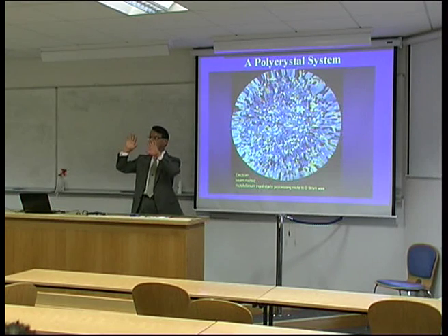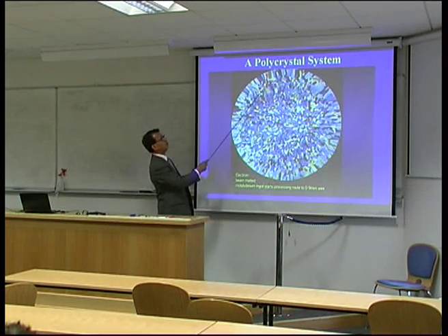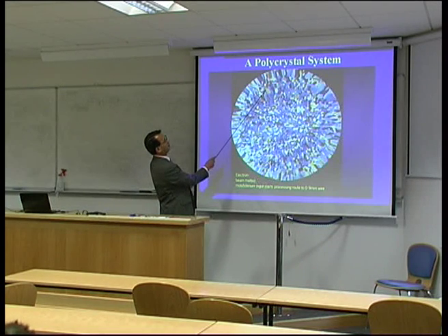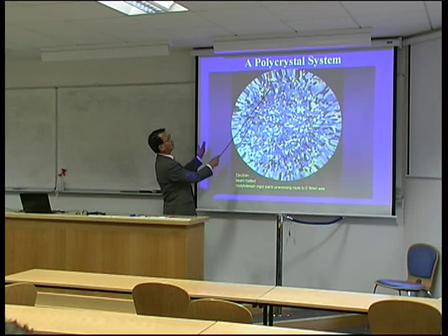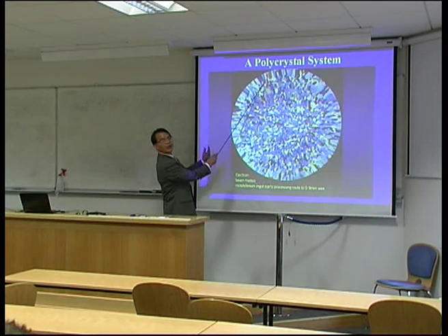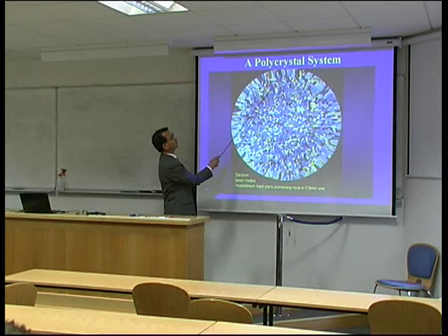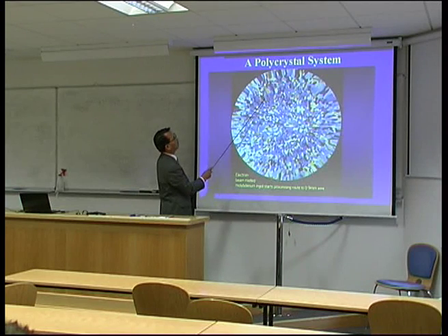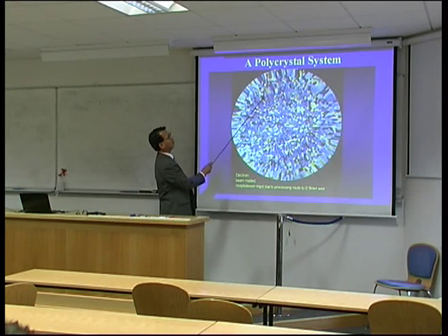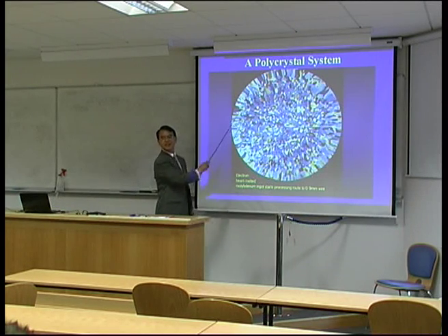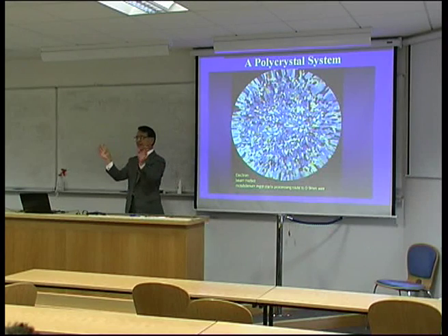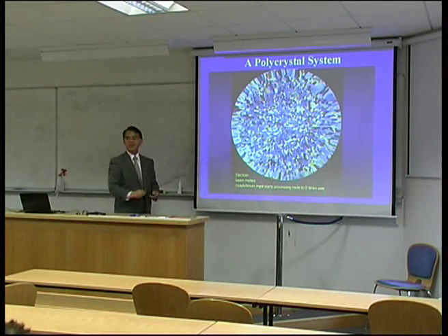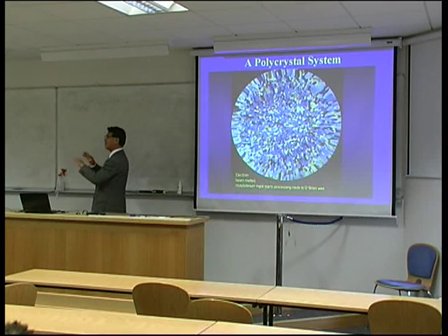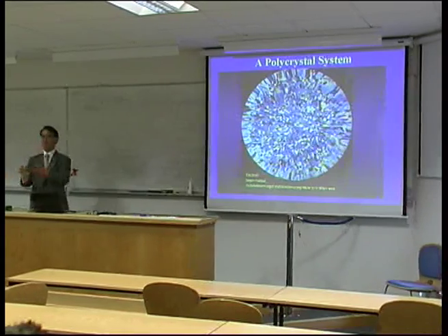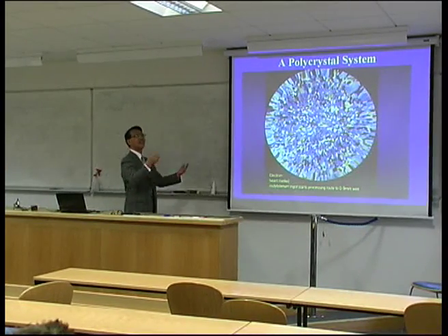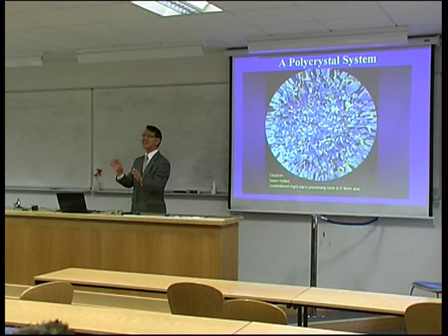Now if you think about a grain boundary, that means two grains meet at the grain boundary. Here, if you look at this, a yellow grain is connected with a blue grain, so this is the boundary between yellow and blue. Another boundary, for example, is between dark blue and green. This boundary may be different from this one, because the relative orientation is different. So in real polycrystalline material, strictly speaking, maybe the same grain boundary can never exist twice. But anyway, if you say it like this, it is very difficult to quantify or characterize the grain boundary.